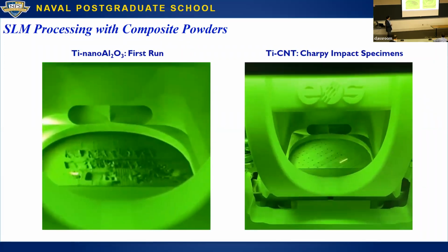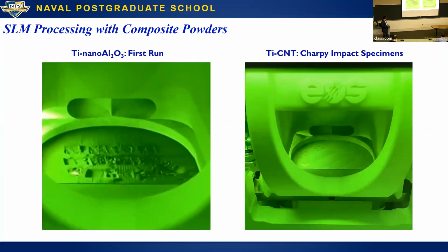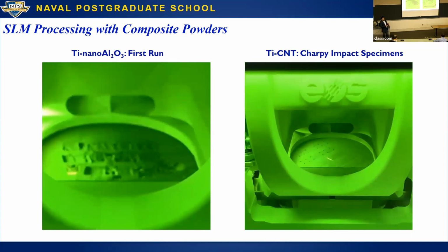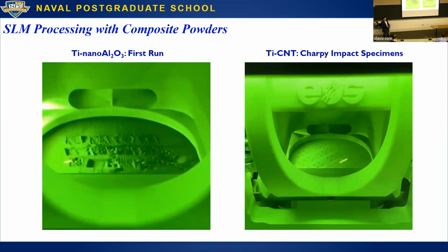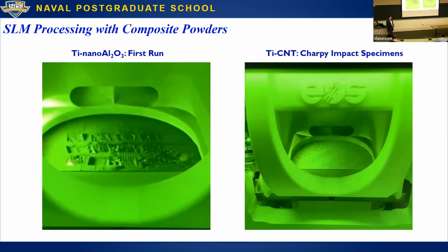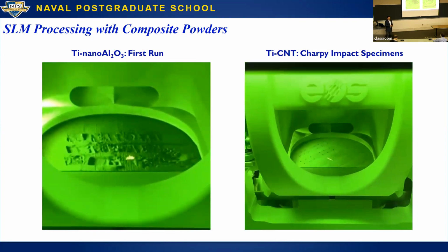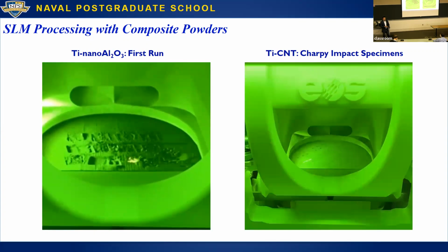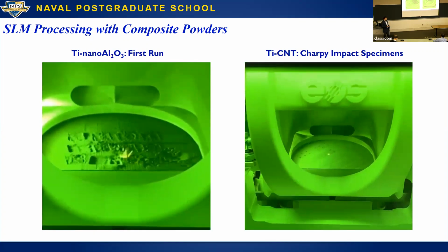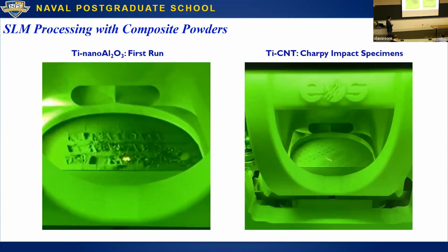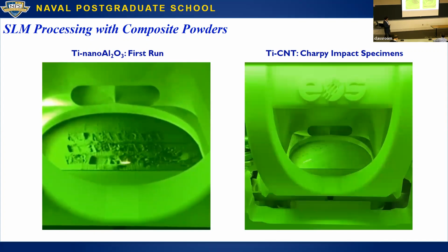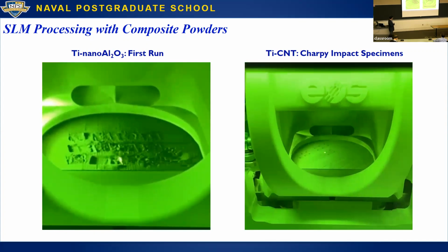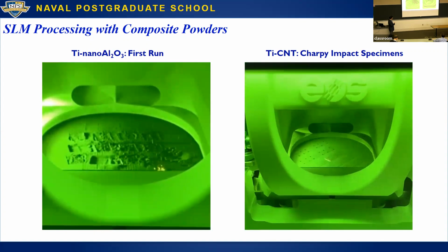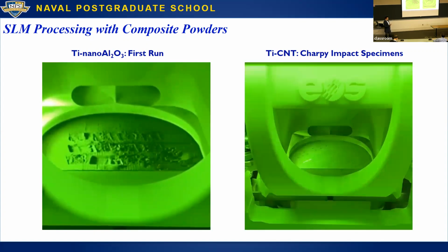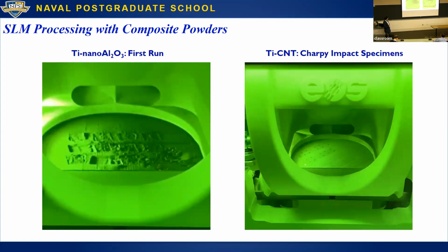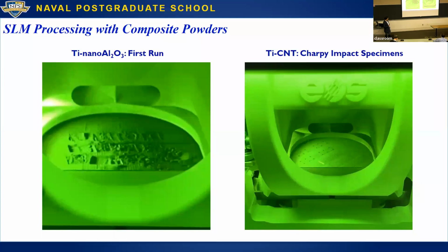We also had not done any optimization of the power. We were using the standard power and energy density for Ti-64, and that was actually too high for working with the aluminum oxide, especially being nano. It was actually dissociating very quickly, we think. We don't have proof for that, but even though this is under inert atmosphere, we were getting these little combustion events that you see going on there.